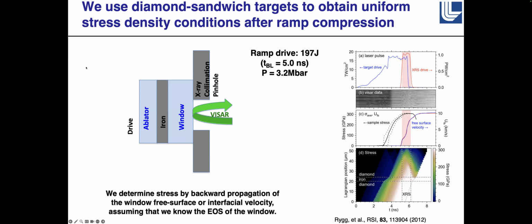And so we've got light from our backlighter, from our helium alpha source that's coming in at many different angles, but only a select set of angles goes through this collimating pinhole. And then we built image plates that we stacked all the way around it. And this shows an experiment where here we've got a space-time, space in the vertical direction, time in the horizontal, that shows how we calculated the stress. We used a diamond ablator and a diamond window on this experiment, iron in the center, and you can see how the stress of the material changed with time.